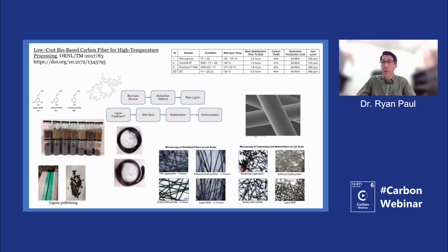This work stopped at the level of starting to scale up, but with the work that was done, we showed that different lignin sources did have potential with a fairly decent carbon yield of about 40 to 45%, and low enough ash content that would make them suitable for these very critical insulation technologies. So this was some of the first work to really try to link together the fundamental lab side with an actual application.